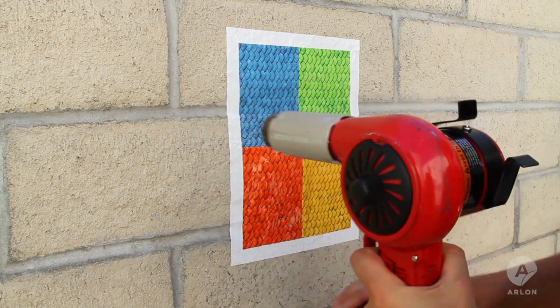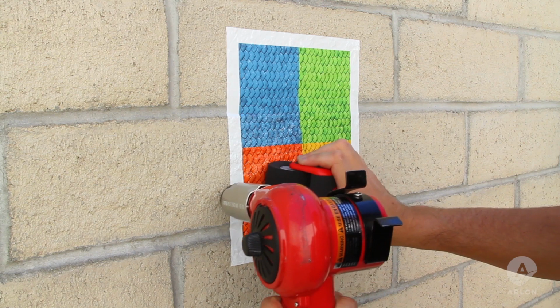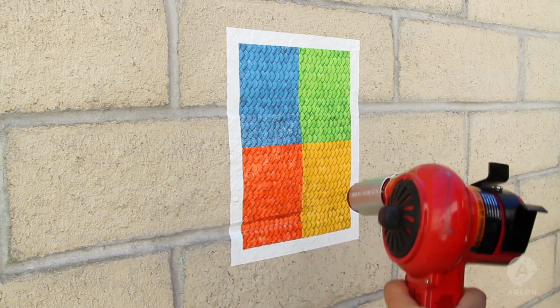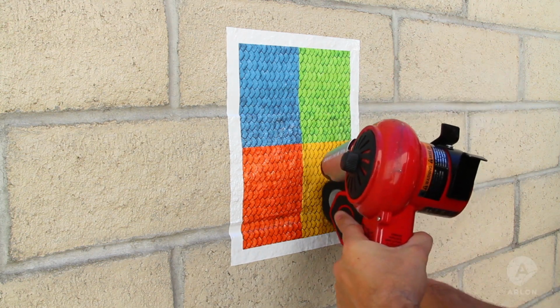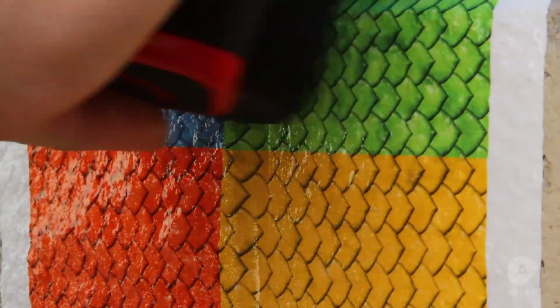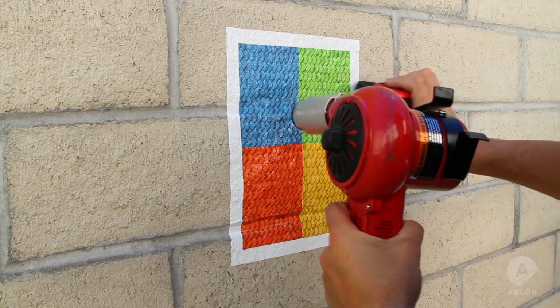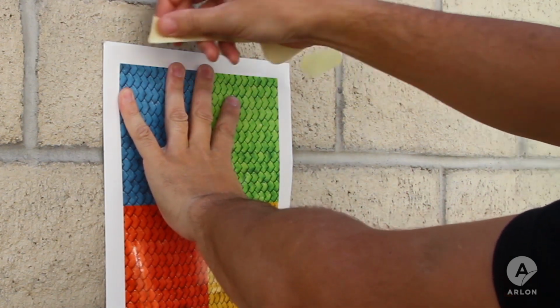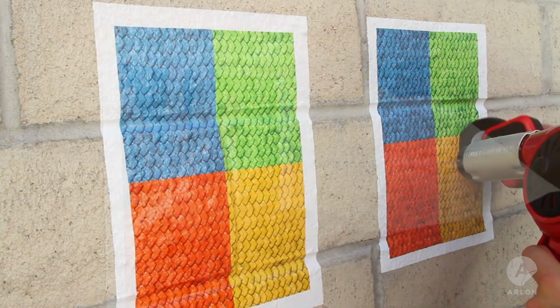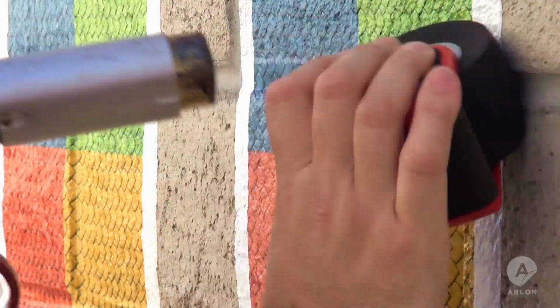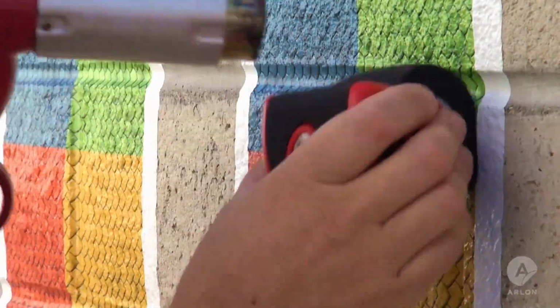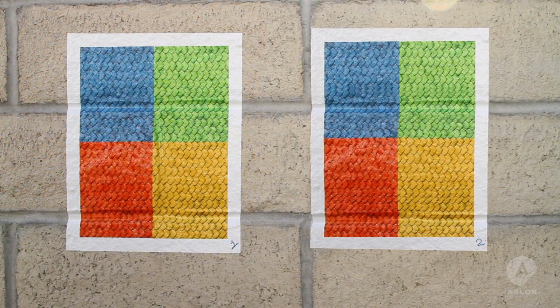Start applying heat in the center of the sample and roll from the center out to the edges, following closely behind the heat gun. Apply slightly more heat and pressure in the mortar lines. Repeat these steps with each media you choose for your side-by-side test. Mark each sample carefully for future reference. Allow the adhesives to set for a minimum of 24 hours.